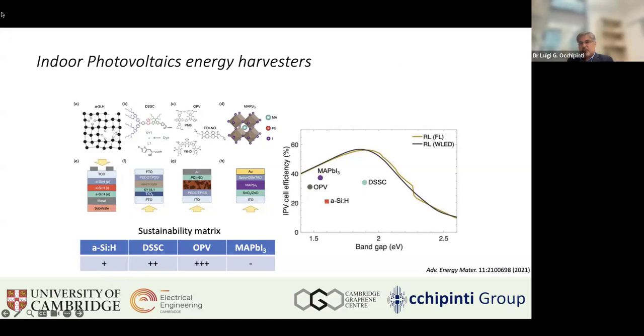Also in terms of DSSC, dye sensitized solar cells, they have a perfect fit in the band gap regime, and typically one of the key challenges for this technology is that historically these were based on dyes like ruthenium-based dyes, which is a scarce element that negatively impacted the overall sustainability profile of the device. Nowadays, there have been a lot of works focusing on replacement of ruthenium-based dyes with organic dyes, and so on and so forth.